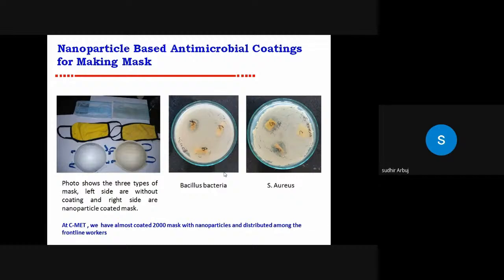So what we did, we developed some silver based nanomaterials and we mixed it with some polymer material and spray coated it on these fabrics. And we tested its microbial activity against Bacillus bacteria as well as S. aureus. So it's giving good activity. And in the presence of light, its efficiency is enhanced by almost 10%. We developed such coatings, and these are being used and distributed. We have coated almost 2000 masks and distributed them among the frontline workers.